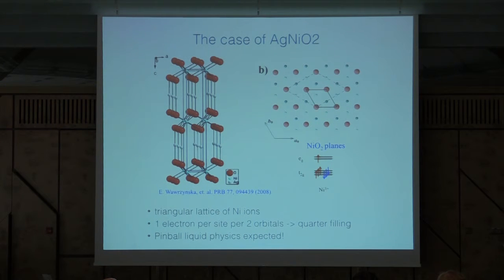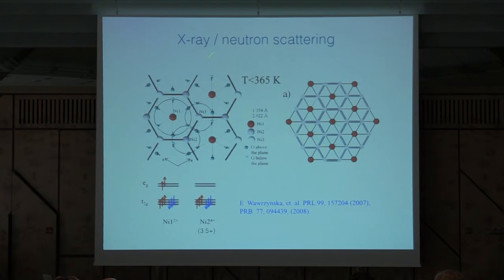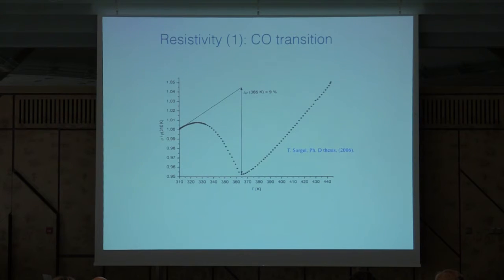So what's the experimental situation then? Well, there have been X-ray and neutron scattering experiments that have observed exactly this threefold order. What they see is that there are charge-rich nickels here, 1 every 3, that have a valence close to 2+. And then these are charge-poor, and on average, they're closer to 3.5. This is sketched here. You can recognize this triangular lattice of charge-rich sites, and then the honeycomb lattice of mobile carriers. In the resistivity, the transition occurs at 365 Kelvin, and it's actually a metal-to-metal transition.